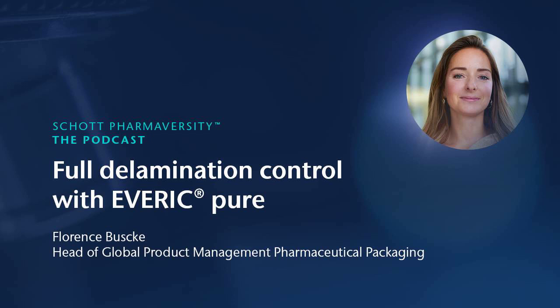So maybe to jump a little deeper into this hydrolytic resistance testing, the pharmacopoeia method for measuring the chemical durability is the hydrolytic resistance test, which is, according to the USP 660, filling the vials to 90% of their brimful volume. And what we know is that the innovative drugs that come now to the market, and it will be the same with the situation we have right now with COVID, if we talk, for example, vaccines, it's not very high filling. So an increasing number of innovative drugs are filled significantly below the nominal volume. This means for a 2R vial, as we just said with a height of 35 millimeters, that we are talking here about 1 ml or lower. So in the case of 90% brimful of a 2R vial, we talk 3.6 milliliters. So this is not the real case.